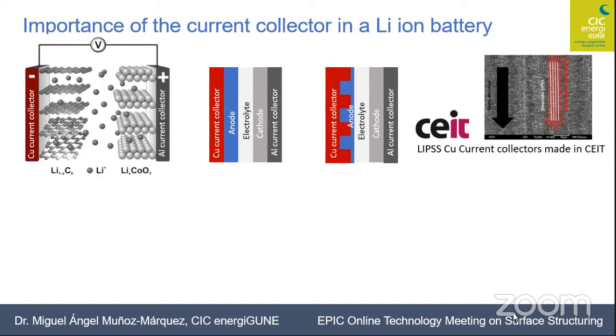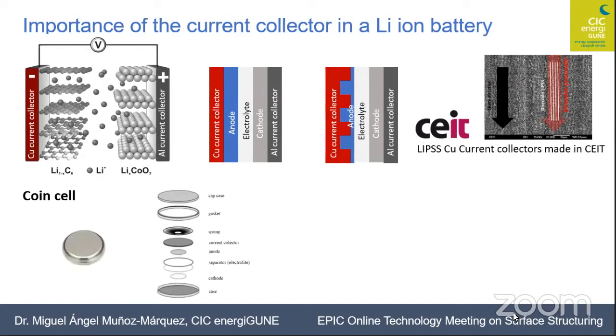Then, as I was saying, we were using the current collectors processed by our colleagues in CEIT with LIPSS. And our idea was first to run a test with different laser parameters, working on small coin cells, the ones that you have in your watch or so on, with a small area of 1 square centimeter, more or less, and then also have a prototype concept of a pouch cell,